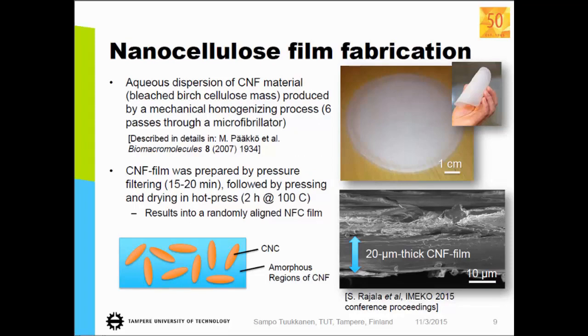So we have fabricated this kind of nanocellulose films. It's not as strong as plastic, but you can bend it a little bit. But if you bend it too much, it cracks. But we are working on that. So this film was basically fabricated from the nanocellulose water dispersion, and you just filter it and hot press it, and then you get this quite dense film.